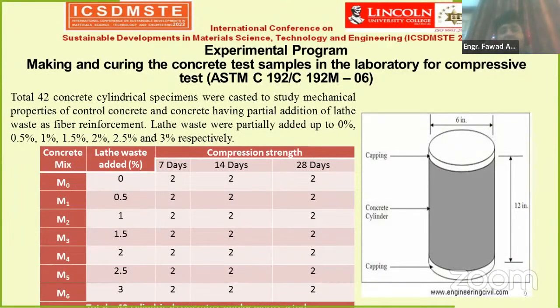A total of 42 cylindrical samples were casted, and the percentage of lathe waste fiber reinforcement was 0.5, 1, 1.5, 2, 2.5, and 3% respectively. Why up to 3%? From past research papers, the optimum dosage was about 1.5 or 2%, so for more clarity I used 2.5 and 3%. The tests were performed at 7, 14, and 28 days of curing age. On the right side, the sample size is shown. The sample size follows American Society for Testing and Materials ASTM C192, meaning I casted the samples as per ASTM American standards.